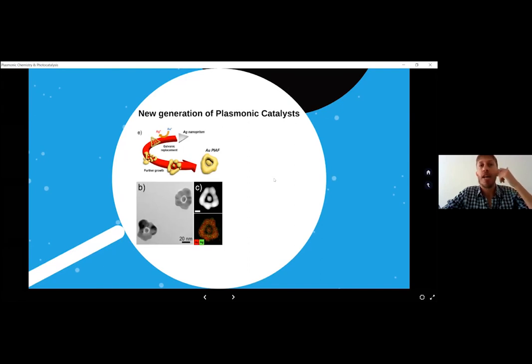We also moved on and started thinking about new ideas or new catalysts specifically designed for plasmonic catalysis, right? There are plenty of different colloids in the literature for many different types of applications, but so far, plasmonic catalysis is quite a new field, and there are very few colloids that have really been thought out for this type of application. So towards that, we also designed new catalysts, which have maybe a bit of a weirder shape, but with the idea that what we need is a really high near field enhancement and absorption inside the nanoparticle in order to have higher temperatures and hot electron production.